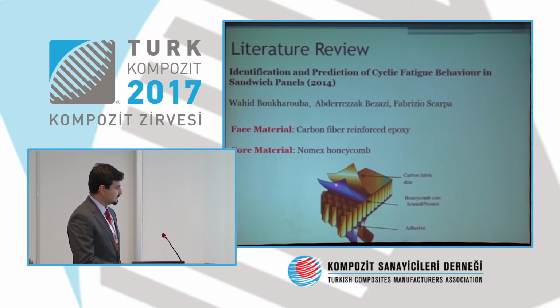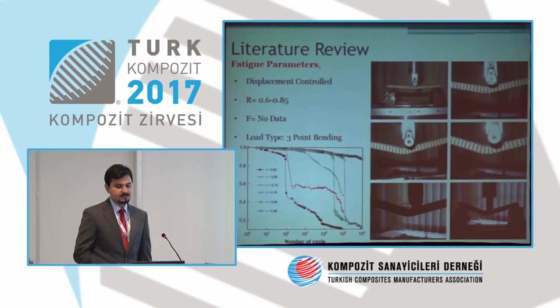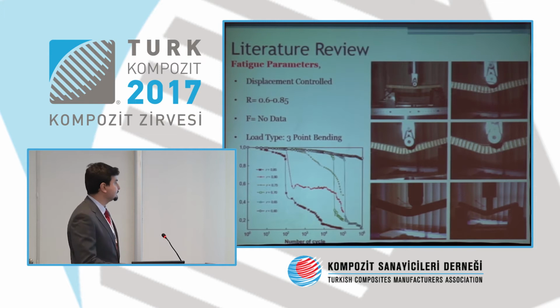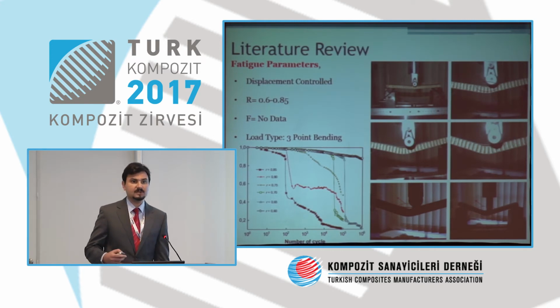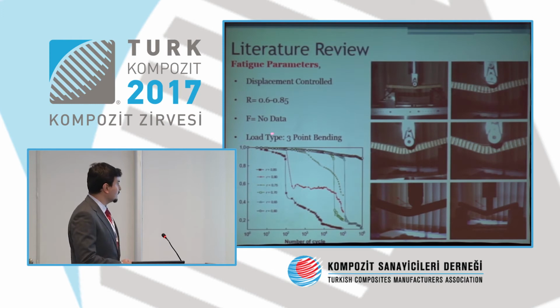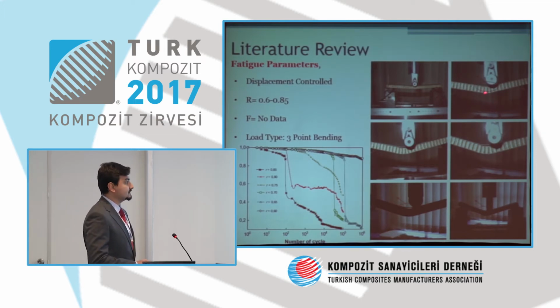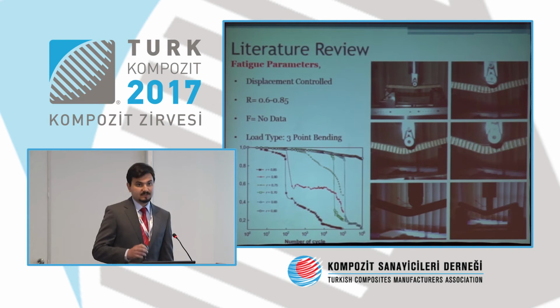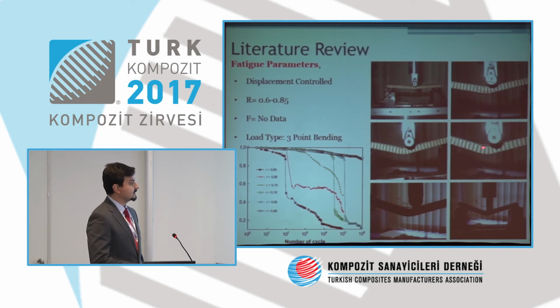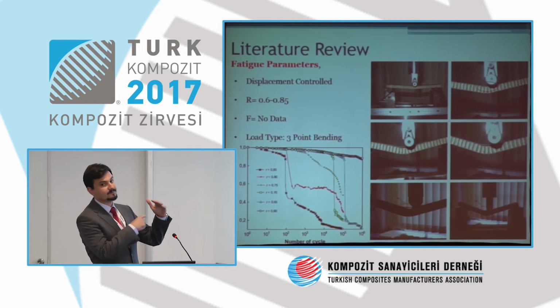And they bonded with an adhesive layer. Here are their results. They made their experiments displacement controlled, and R is the stress ratio for fatigue. And load type is 3-point bending load, as you see here. They determined the very important thing, the failure mode. They claim that the first failure mode occurs in the intermediate layer, here, between the core and face sheets.